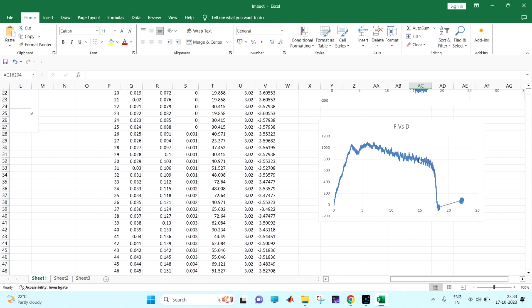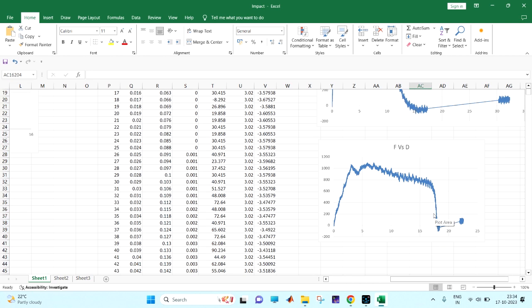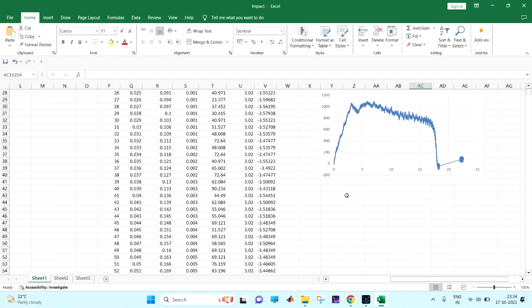The core is get compressed and while compressing some load is reduced but it is still maintaining some. And you can see the displacement has not returned back. Means the material has no spring back and all the energy is absorbed here. So that's the good thing with this type of material. And all this behavior you can read it from there.